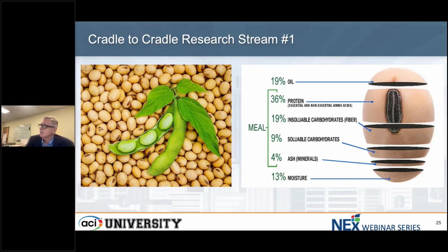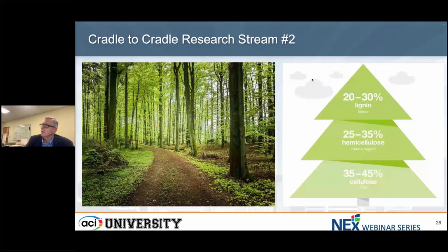This is our second research stream in our labs. We take trees and we take the lignin out of trees. The cellulose is made into paper, and we take the 20-30% lignin, which is the binder or the glue in the tree, and we put that cross-linker on, and now it can cross-link and make a cross-linked polyurethane, a thermoset polyurethane that nature can recycle.